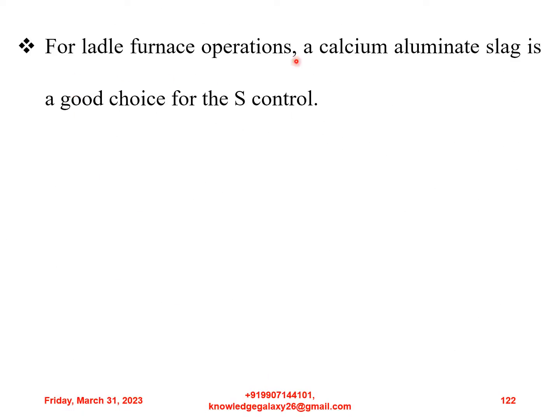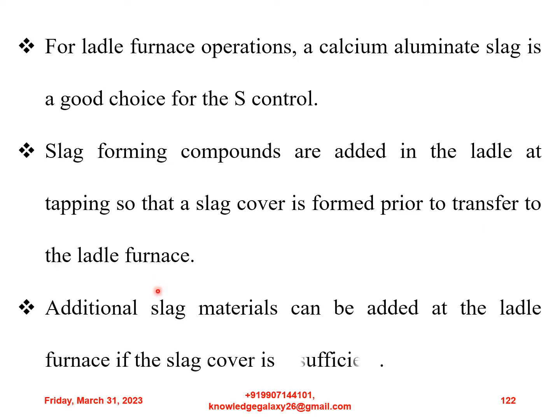For ladle furnace operations, calcium aluminate slag is a good choice for the sulfur control. Slag forming compounds are added in the ladle at tapping so that a slag cover is formed prior to transfer to the ladle furnace. Additional slag materials can be added at the ladle furnace if the slag cover is insufficient.